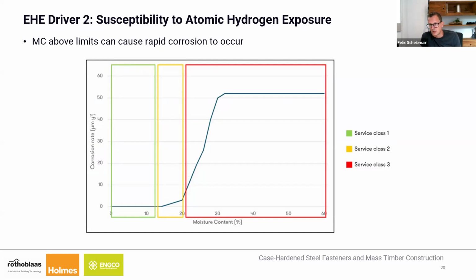This here's a reproduction from some research that was done some time ago, but you can see that in terms of your corrosion rates, if you're in roughly service class 1, so from let's say 1 to 12% moisture content, you really don't see any corrosion at all in your fixings, and it doesn't matter as much if you've got treated timber or not. Once you're in that space, there's not much corrosion happening. Once you get into service class 2, you do start to see a slight increase, but again, it's reasonably manageable. But what's important to consider is that when you step out of service class 2 into service class 3, the acceleration is very rapid.